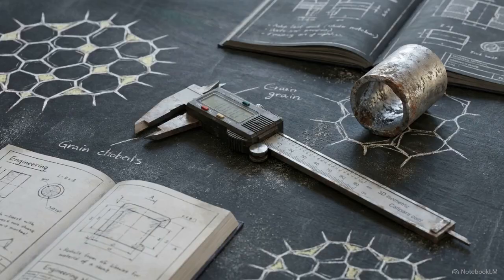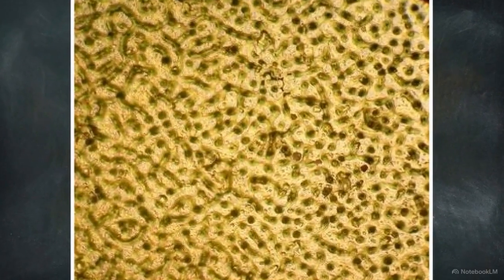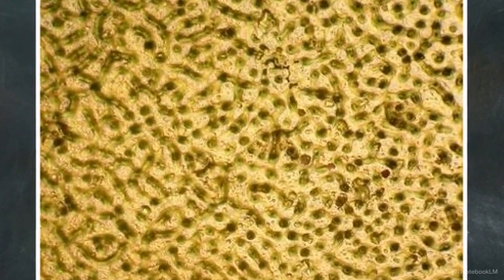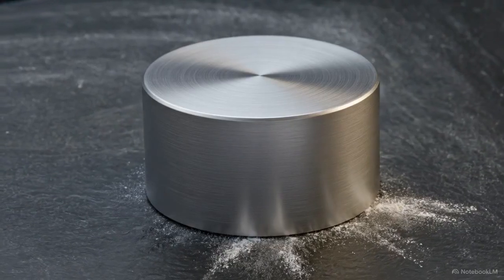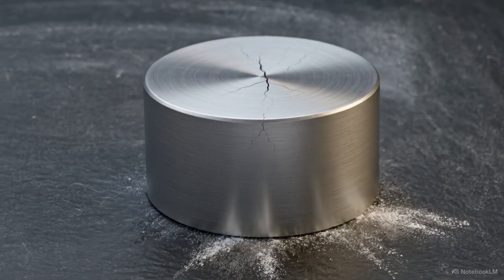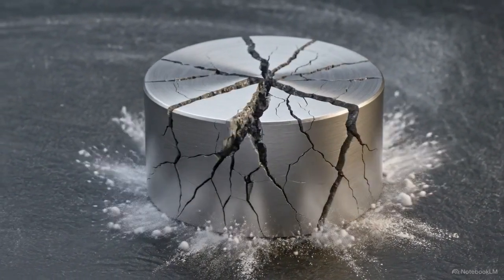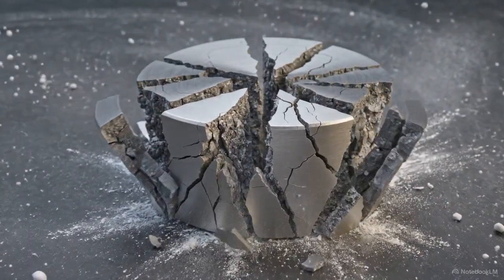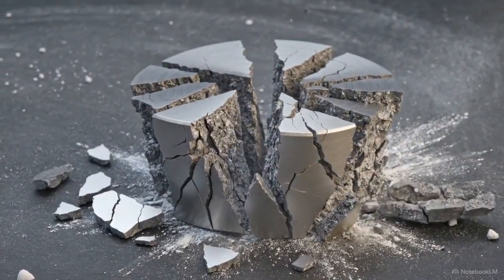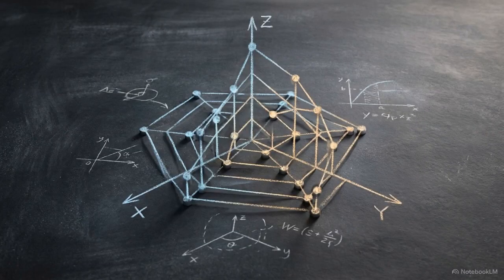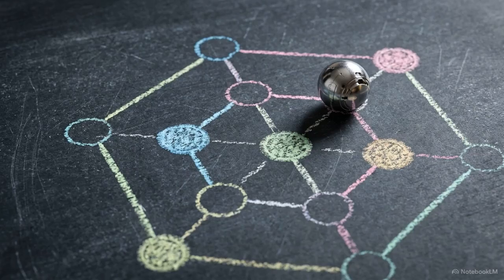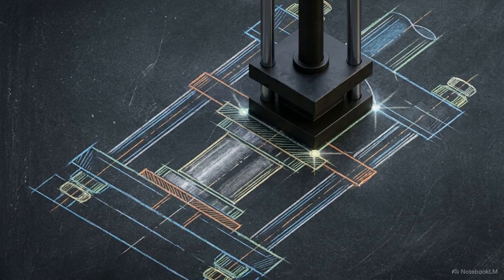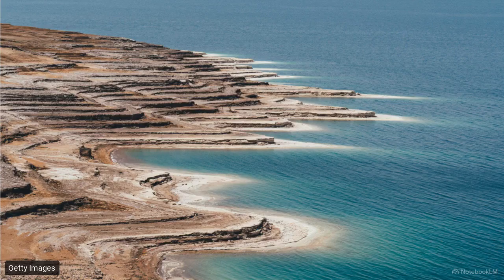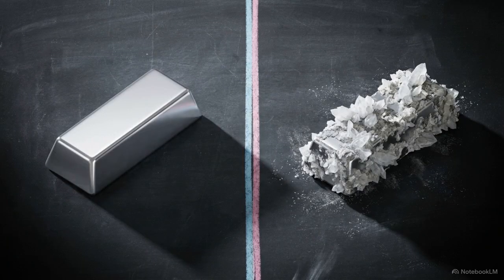This paradox illustrates a central logic in modern materials design. The energy trapped within severely deformed, work-hardened grain boundaries becomes a liability the moment it touches a conductive electrolyte. Artificially maximizing a single metric, like pushing physical hardness to its peak, creates a structural vulnerability elsewhere. Successful alloy design involves calculating the balance between phase chemistry boundaries, mechanical processing techniques, and the operational environment. In material science, success is measured by the calculated management of inevitable structural trade-offs.